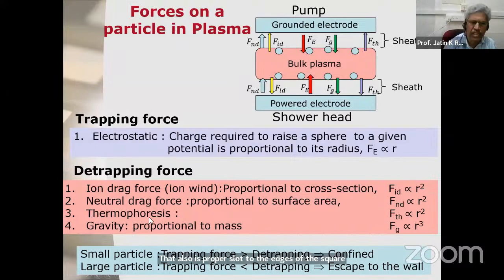Then there's thermophoresis, a detrapping force. That is, if there is a temperature difference between the plasma bulk and the ground, there is a temperature gradient. It pushes the particle from one side. It's called thermophoresis. And fourth is the gravity. Gravity will bring it down.